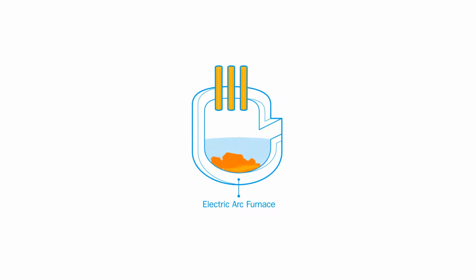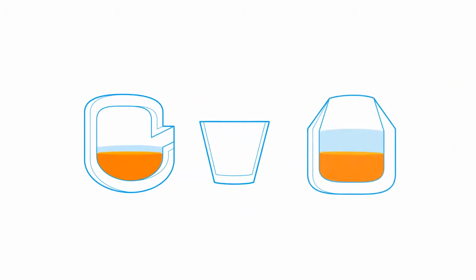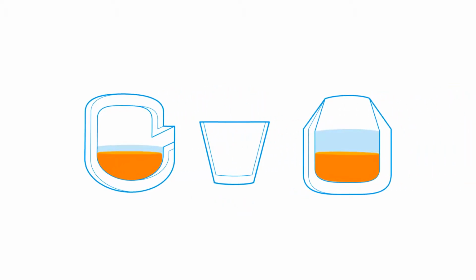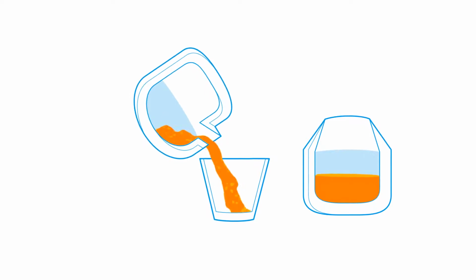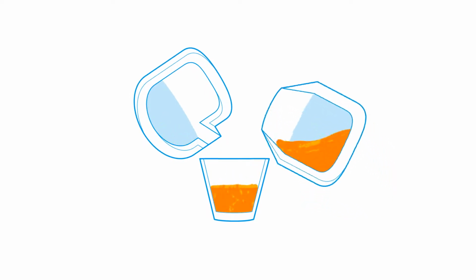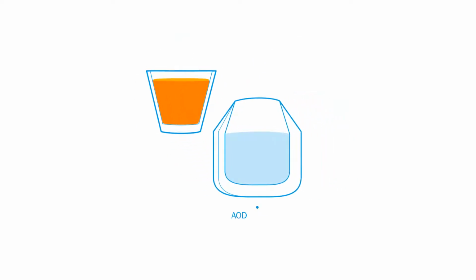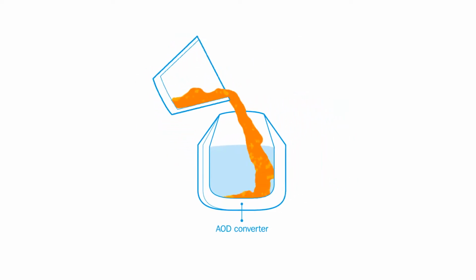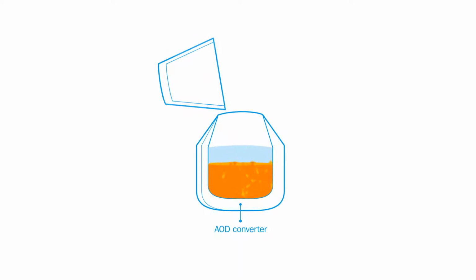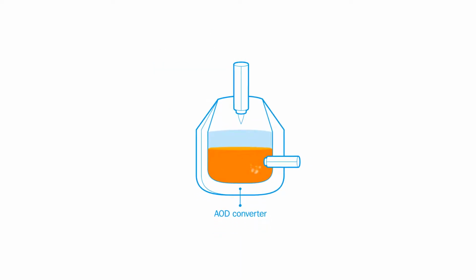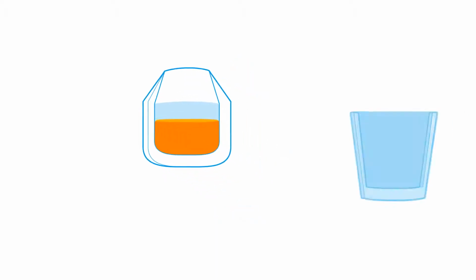In the steel melting shop, an electric arc furnace is charged with recycled steel and other raw materials, such as nickel, molybdenum, ferrochrome, and coke. Once the charge has melted and the slag is removed, the melt is mixed with ferrochrome melt and transferred by ladle to the AOD converter. In the AOD converter, carbon and sulfur are removed, and the alloying is made to create the specified stainless steel grade.